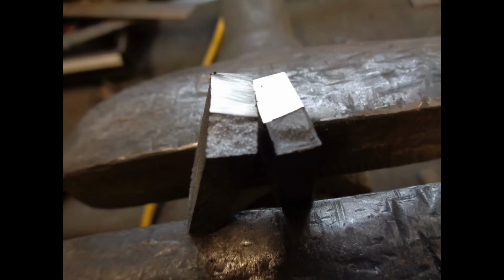Performing the nick test, you can see that it takes 2 hammer blows to break the top off, and the sample bent before breaking. Looking at the grain, you can see that it's smaller and more refined than the previous sample, which is what made the sample slightly tougher.